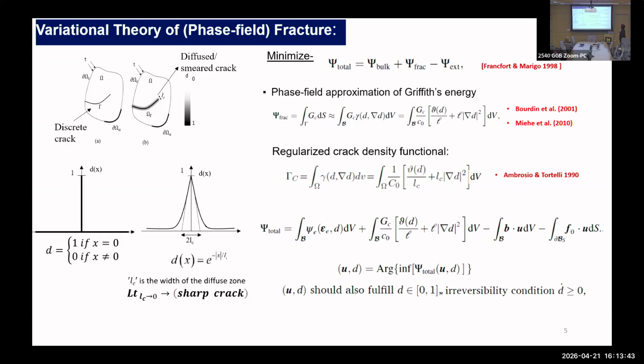Okay, so the key point that we need to focus on here is that the fracture energy is described over the crack surface area, whereas this bulk elastic energy is integrated over the volumetric domain. So it's basically one over the surface area term, and this one is the bulk volumetric term. Okay, so theoretically it was possible, but numerically it was quite challenging to implement until the late 2000s work came up, where the description of this order parameter, as it is more formally known in the broader domain of phase field approximation, was introduced to describe the damage field.